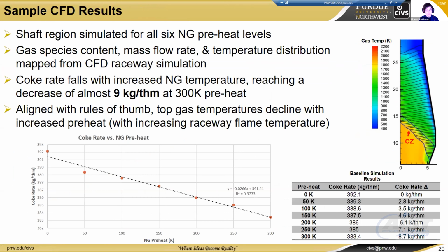And on the shaft side of the CFD results, we have all 6 levels of the natural gas preheating, including gas species content, mass flow rate, and temperature distribution mapped from the CFD Raceway simulation. So the Raceway is kind of an intermediate step between the shaft and the tuyere. And then the coke rate, you can see that the coke rate falls with increased natural gas temperature, reaching a decrease of almost 9 kilograms per ton of hot metal at the 300 K preheat level. This aligns with our rule of thumb that the top gas temperature declines with increased preheat, but it results in an increased Raceway flame temperature.